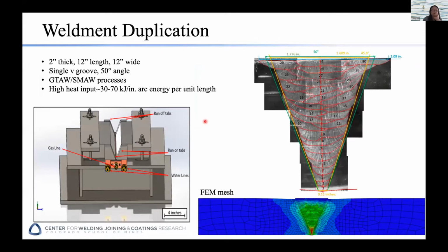So that's why in our test, we want to duplicate the weld first and then test the susceptibility of this weld to cracking. Okay, so first we made this setup in the lab. You see this is where the 2-inch thick steel plates are clamped on, and then we have the single V groove to deposit the welds. This is all designed based upon the inputs from our industrial collaborator, simulating the real industrial fabrication procedure. Okay, so this is showing how the weld looks.